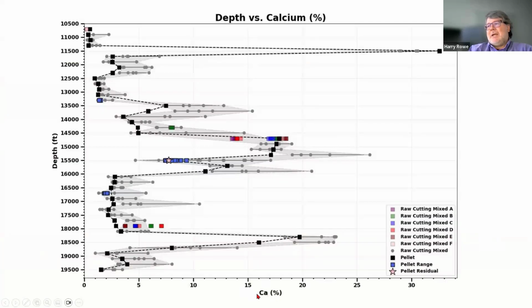Is that this percent calcium versus depth? These are individual cutting samples going in the lateral. The dark gray dots here, that's just scanning cuttings. This is a pellet. And what you find in this type of lithology is the pellet is generally lower in calcium than everything else or most of the samples that are measured here.